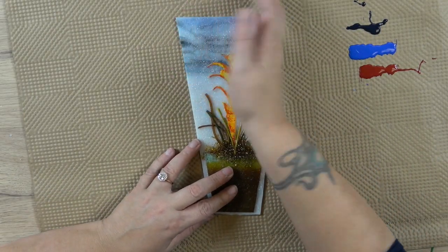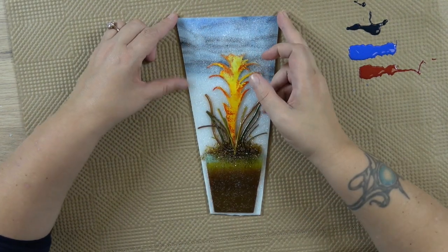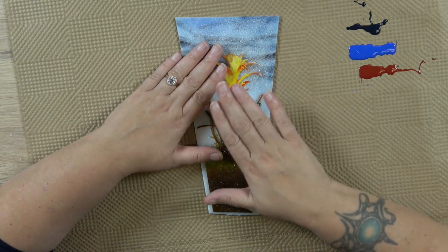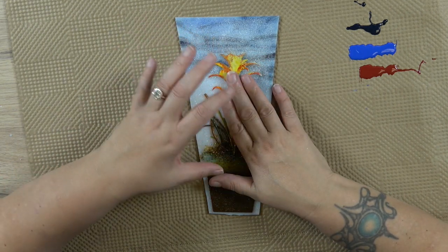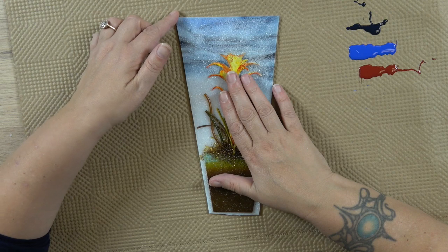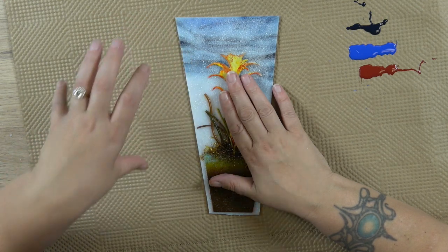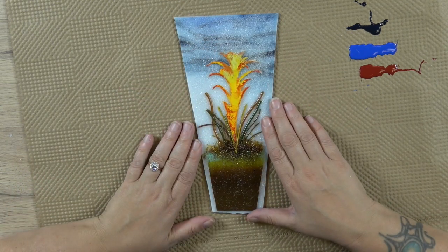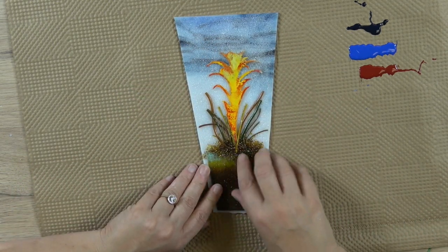Don't forget to take a diamond pad to your corners before you fire it, because the next firing is 1160, and it's not going to be enough to make those look a little bit satin and nice. So grind your corners. Do not forget, before you tack fuse here. This is perfect. Look at that.